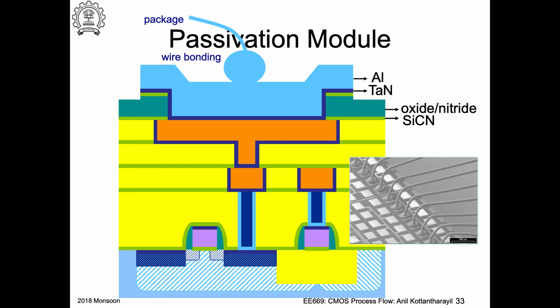Okay, so you can see here this orange thing is the copper, and then you have this silicon carbide, silicon carbon nitride, and then you deposit oxide and nitride. Okay, and then there is a tantalum nitride. So these nitrides are very important because they prevent the diffusion of water. So the copper is protected. On the top is aluminum. Aluminum is quite robust because you naturally have one very thin layer of aluminum oxide, which would passivate and protect the aluminum.